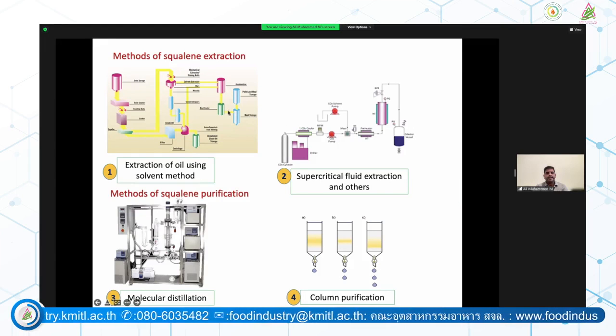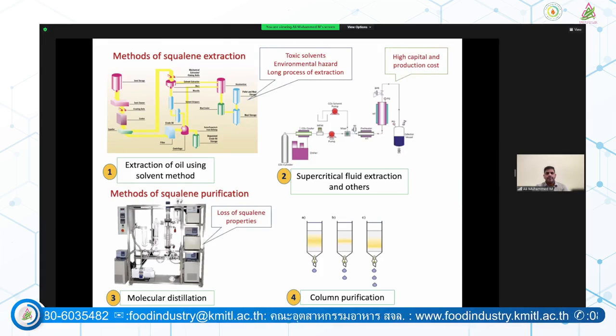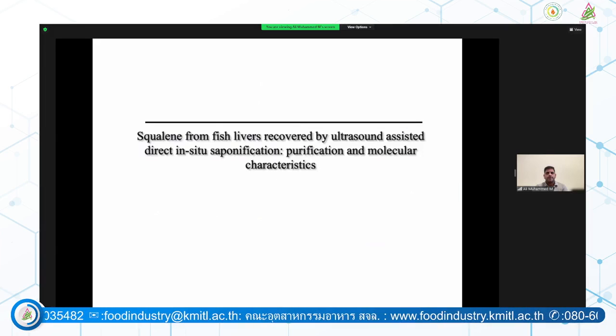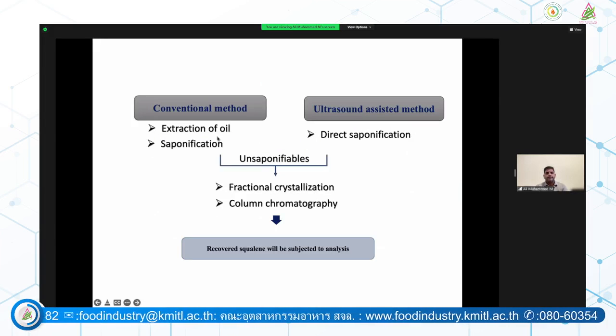Still, after production, they have to go through a complex extraction process. I tried to make this extraction process simpler, because just a simple chemical reaction can extract a significant amount of squalene. The conventional method used in industries involves various processes. In the laboratory, we tested oil extraction first, followed by saponification. After the saponification reaction, the unsaponifiable fraction contains the squalene, because squalene cannot undergo saponification.